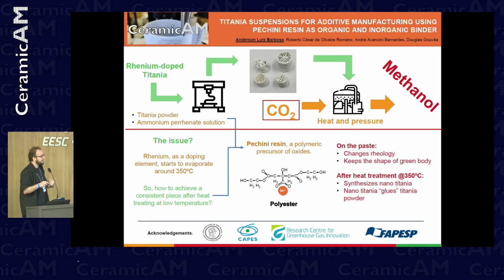And the issue we have is that the ammonium perrhenate, the rhenium actually, as a doping element, starts to evaporate from the surface of the titanium at a relatively low temperature, at 350 degrees. So how can we have a solid piece without reaching the sintering temperature of the titanium? The solution we got is to use the Pechini resin. It's a polymeric precursor of oxides, so you have a polymeric chain with the cation of your metal that you turn to the oxide.